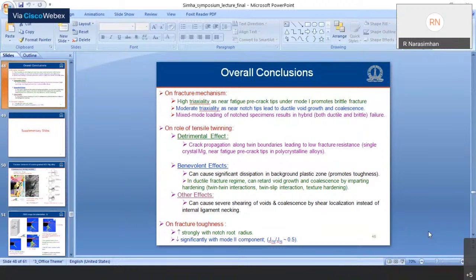whether favorable slip like basal slip gets triggered, and you are right in the sense that these soft slip modes go in conjunction with twinning. As I showed you in the optical metallographs, there is evidence of slip taking place inside twins. So you have a combination of slip and twinning taking place in magnesium. I think together they would contribute to dissipation, but I feel that there is a marked role for dissipation due to twinning in this case.